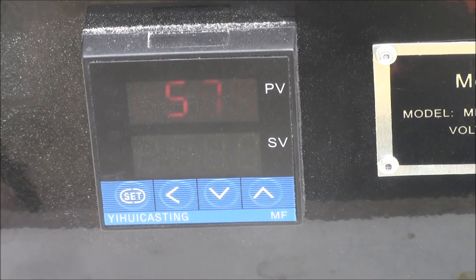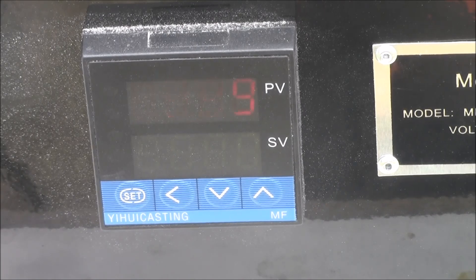Magnesium melts at 650 degrees Celsius so I set mine to around 700. At high temperatures magnesium will react with the air to form the oxide which in this case will be slag which is not what we want. Just scrape off any of that forms.